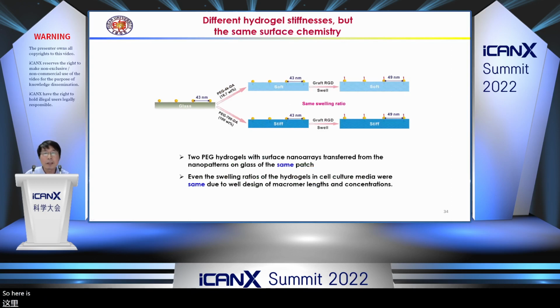So here is a more brief schematic presentation. Because we transfer the already formed gold nanoarray to the PEG hydrogel, we can control the surface chemistry. Another key factor is that our nanoarray was generated on PEG hydrogels, which are very potent in resisting non-specific cell adhesion. In this way, protein adsorption could be ruled out completely, and then we can examine whether or not the matrix stiffness effect does work.